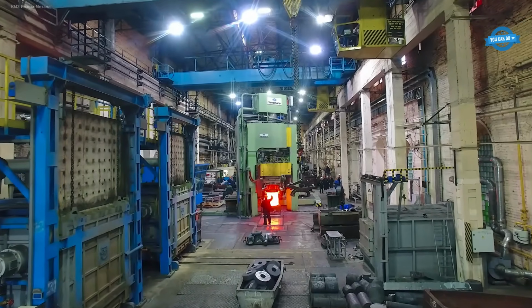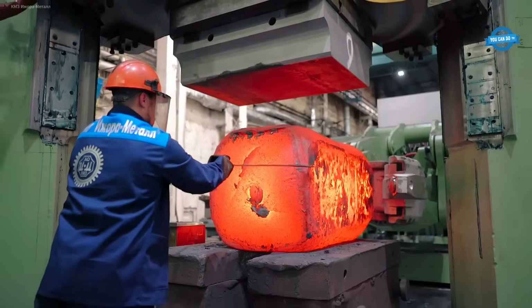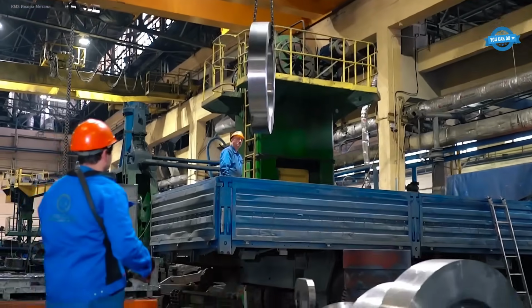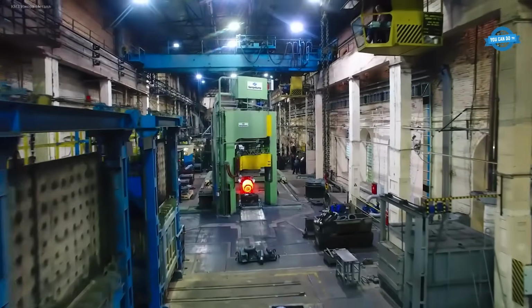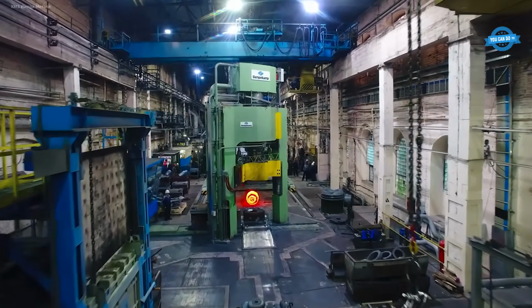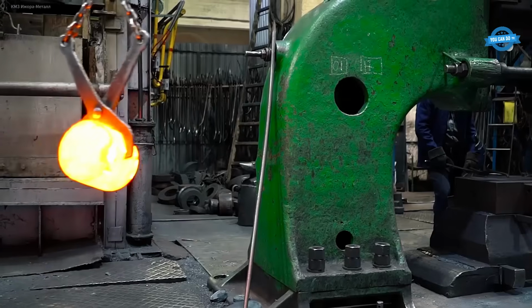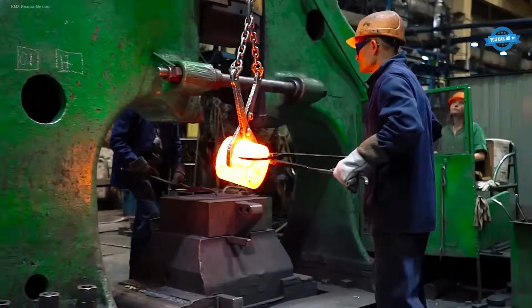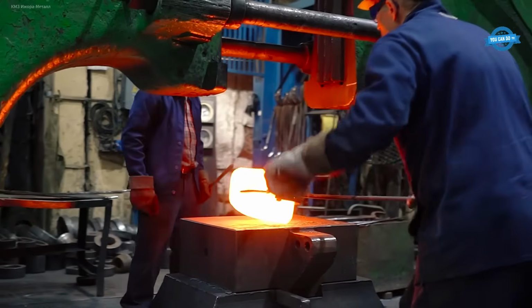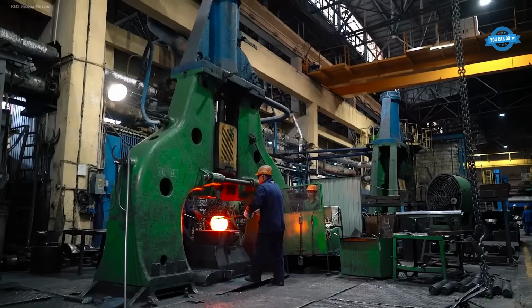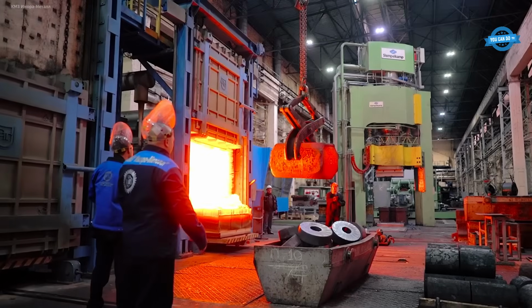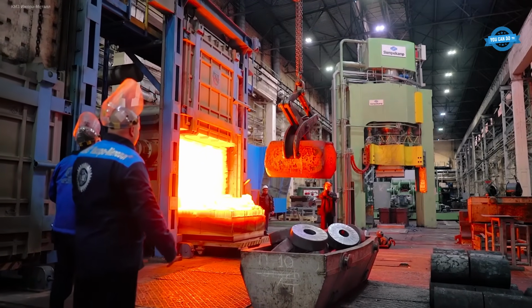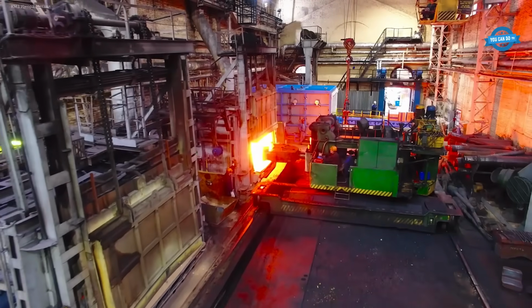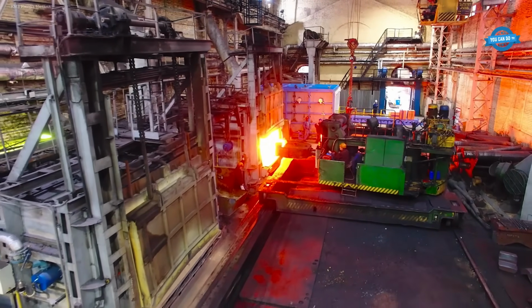KMZ Izhora Metall specializes in the production of open die forgings and billets using high alloy and heat-resistant steels, non-ferrous metals, and specialty alloys. Equipped with hydraulic presses rated up to 2,000 tons and manipulators up to 10 tons, the facility supports forgings up to 10,000 kilograms. Heat treatment furnaces feature automated controls with plus or minus 5 degrees Celsius stability.